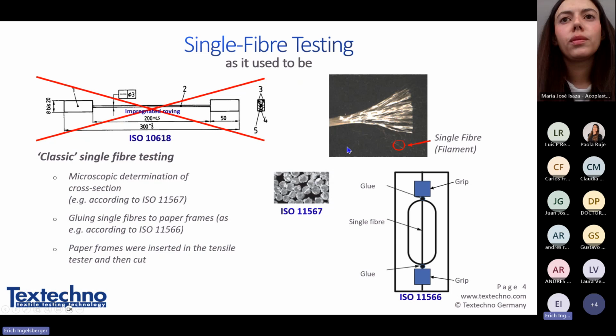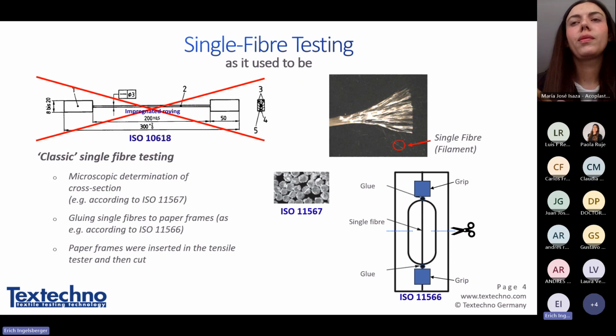Then you have two grips of the tensile tester, upper grip and lower grip. The final step before being able to test is you cut this paper frame here with scissors, and then you can start tensile testing. That means it will take a little bit of preparation time and energy to test such an individual fiber according to the ISO test method.